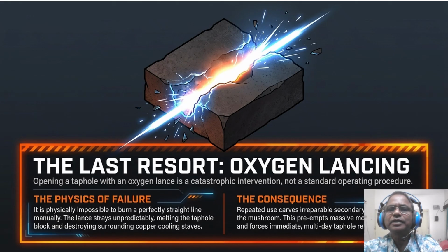So this causes a multi-day taphole repair activity, which takes a lot of time. Repeated lancing carves secondary cavities inside the mushroom, which leads to massive molten breakout. So if you find yourself reaching for the lance, your process has already failed. We use the science of clay and drilling to ensure that the lance stays on the rack.